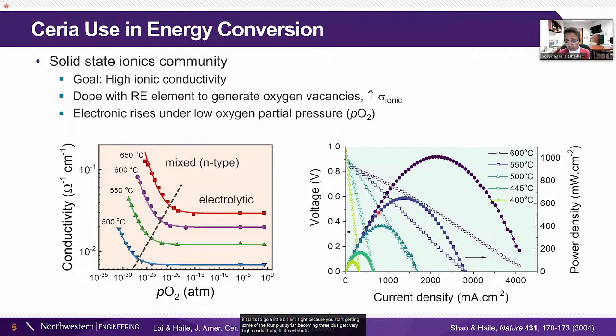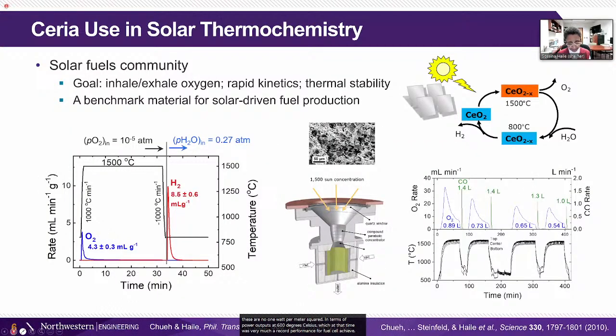That contributes to its usefulness as a fuel cell electrolyte and a component in the fuel cell anode. And so from that, we get these record power densities. These are 1 watt per centimeter squared in terms of power output at 600 degrees Celsius, which at that time was very much a record performance for a fuel cell achievement.